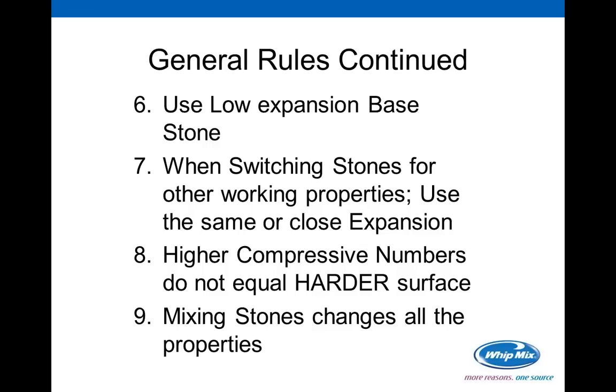On the other hand, if you shorten the water, you're also going to get a faster setting time and a shorter working time. And the opposite is true by adding water. But within that little space, you're really not going to see a lot of difference. Now, I will tell you where you will get the difference, and that is back to those technicians who are trying to pour 10, 15, 20 impressions at a time. You mix up a big batch of material, and you're really studious, so you mix it correctly. You get to impression number 9 or 10, and you have a problem for one reason or another, and it stalls your speed. As you get back to 11 and 12, you'll notice that your stone is starting to set up, so you go to the sink and you add a little more water.